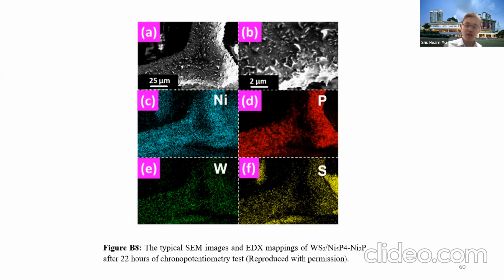For my understanding, the interface is not very clear in the study, and also in the TEM I couldn't identify the interface. So it's more likely that the DFT performance is trying to find a trend. We have the MoS2 structure or WS2 structure. Then we remove the sulfur atoms and put in phosphorus, and we want to see whether the Gibbs free energy of hydrogen adsorption will be reduced or not. We find that after we introduce the phosphorus, the Gibbs free energy can be reduced. So we believe that the basal plane, which is originally inactive, is activated, so that increases the number of active sites.